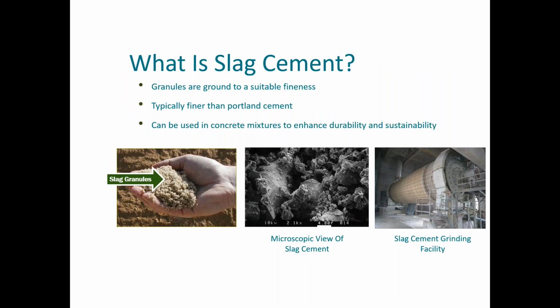And interestingly, this handful of stuff this person is holding in this picture is what slag cement looks like before it's ground. So it's not white before it's ground, but after it's ground, it becomes white. If you look at a microscopic view of slag cement, you can see that it's angular. You've got some different particle sizes, and typically it's going to be slightly finer than Portland cement. And this mill to the right, the grinding facility, is a pretty standard mill. If you've been around a cement plant that has a ball mill, it's the same exact type of equipment. So it's ground on the same type of equipment that you would use to grind cement.